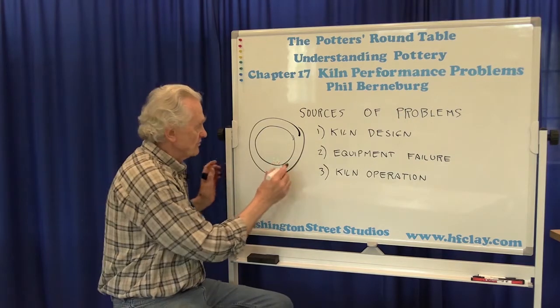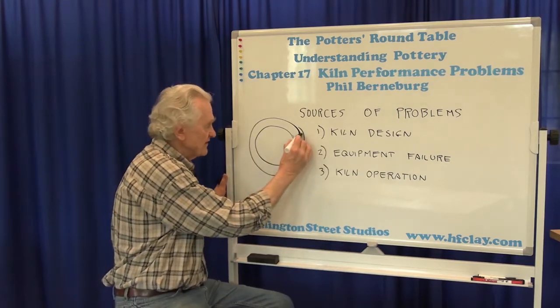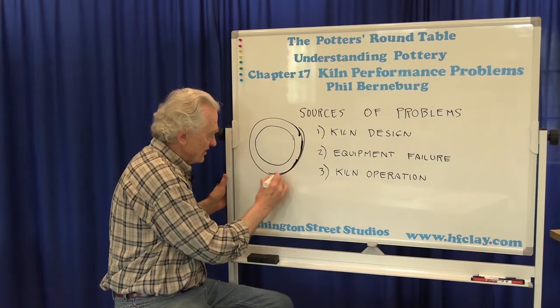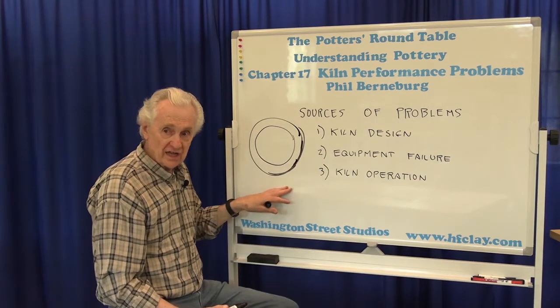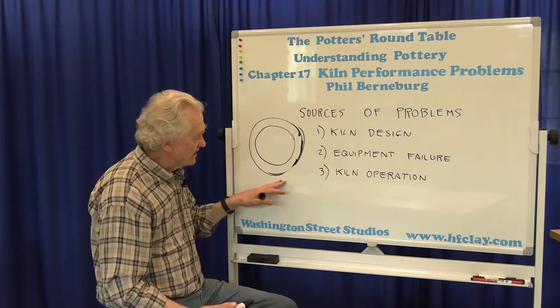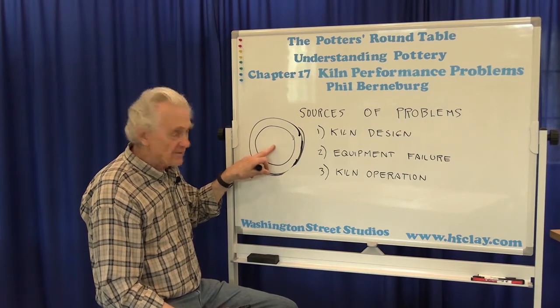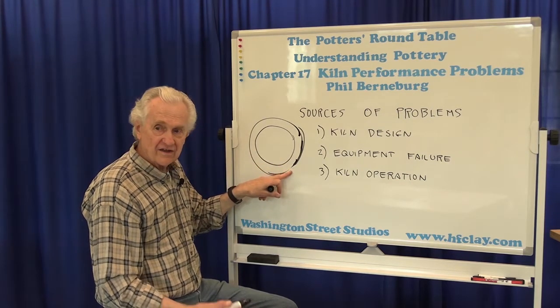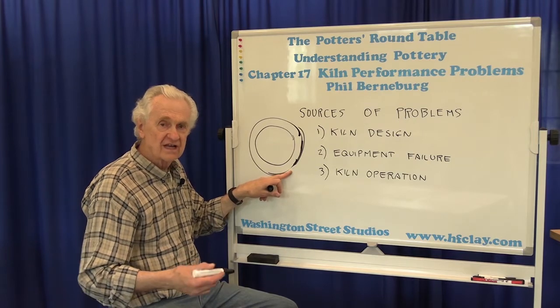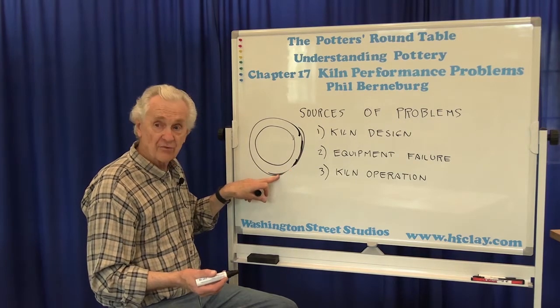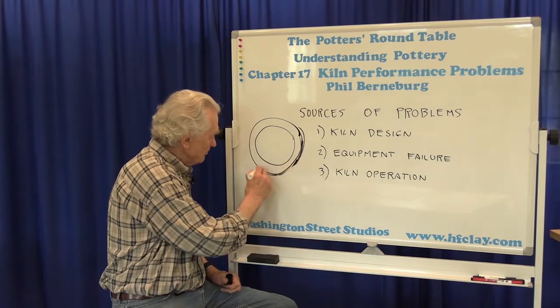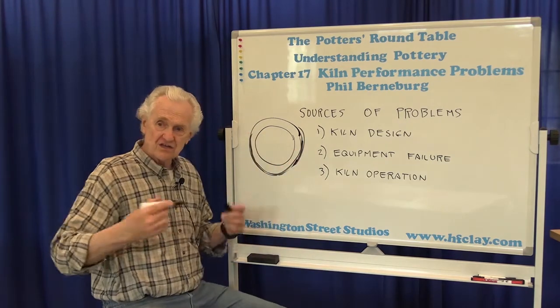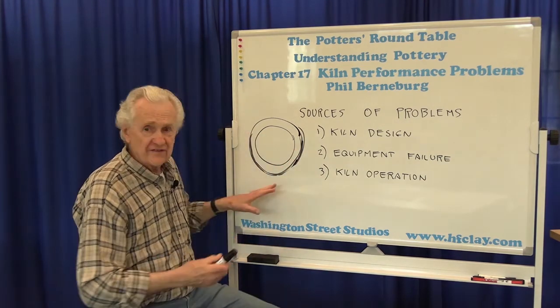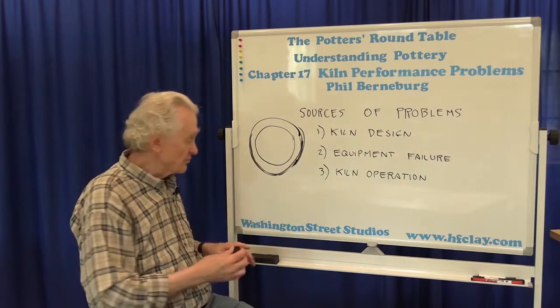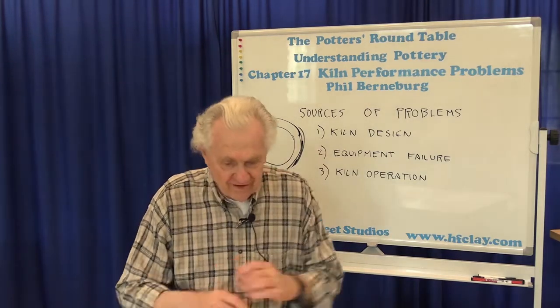When the bricks start to crumble, they don't crumble on the inside, they start to crumble close to the outside, just inside the metal shell. And if you start to see that, that's because the acid fumes that are coming out of the kiln, when they meet the air on the outside of the kiln that has moisture in it, form acid and start to attack the bricks. So if you start to see this crumbling just inside the metal shell on the outside of the kiln, that's a good indication that you're really not venting your kiln properly. Okay, so those are some problems with electric kilns.